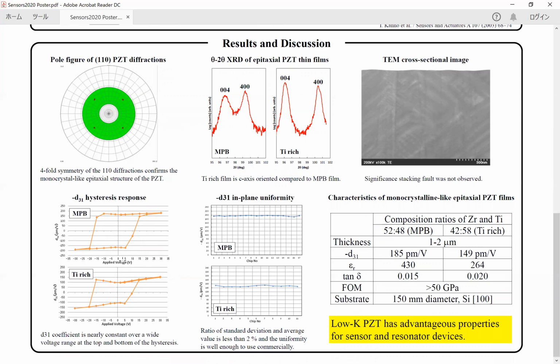The measured D31 coefficient is nearly constant over a wide range at the top and bottom of the hysteresis, and the magnitude of the D31 coefficient is nearly symmetric with respect to applied voltage polarity. Consistent with the polarization hysteresis measurements, there is an asymmetry of the positive and negative coercive voltage of the D31 hysteresis. This effective shifting of the hysteresis loop to the left is attributed to a positive internal bias field within the PZT.